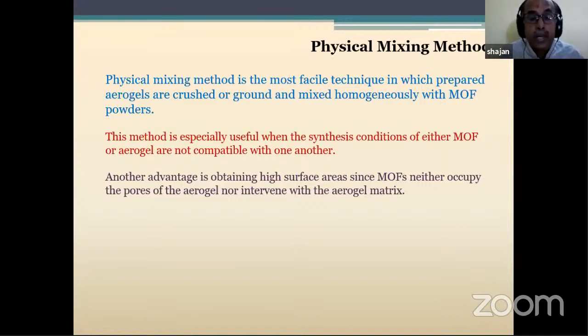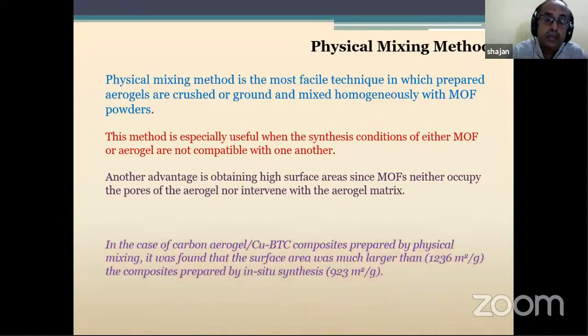And this is also advantageous in getting high surface area, because, as you will see later in our experiments, sometimes we lose the surface area of the aerogel. The aerogel will have a high surface area, and when I add the MOF, it reduces the surface area in certain cases. But all these drawbacks are overcome in the physical mixing method.